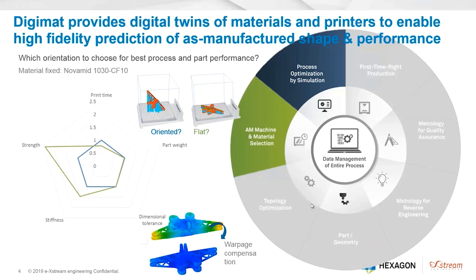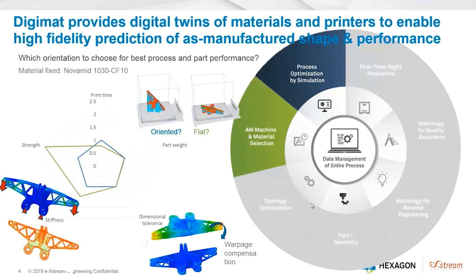We can then move on with structural analysis to assess both the stiffness and strength performance of the part. This is done by running a coupled finite element analysis accounting for the local manufacturing history and the local microstructure of the material. The simulation predictions provide a very strong indication of which is the best orientation to choose.